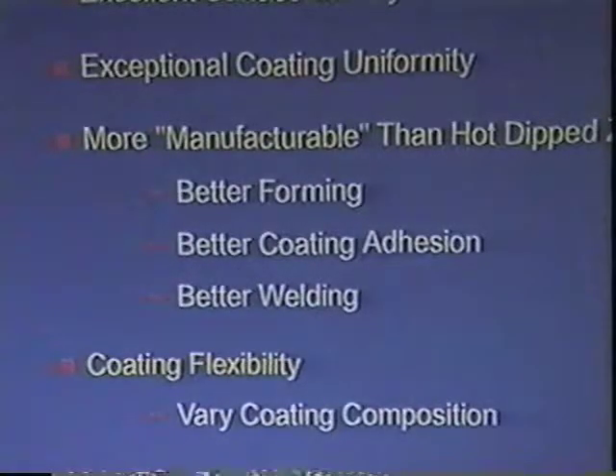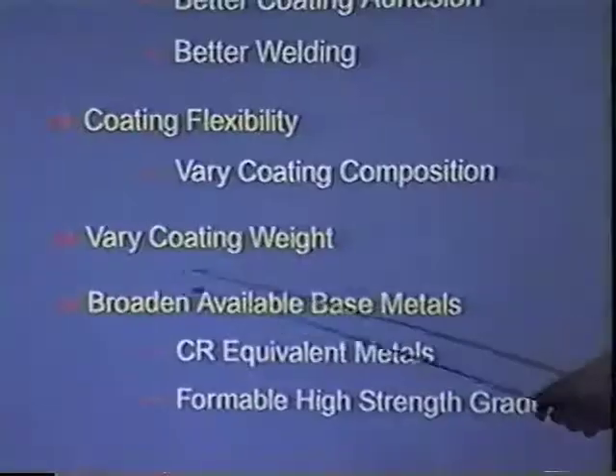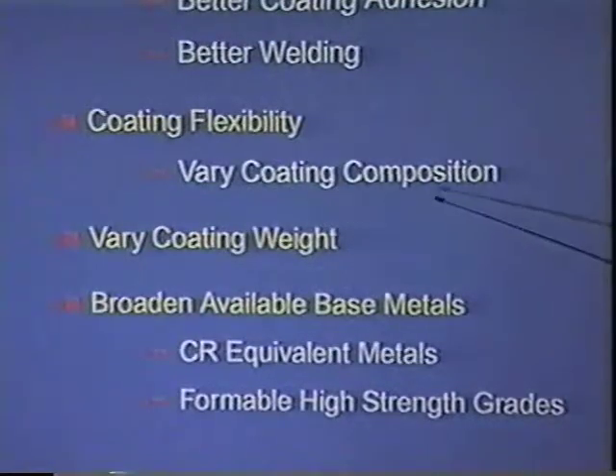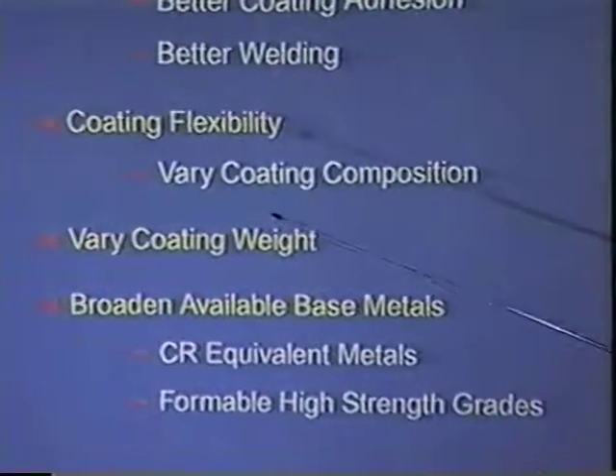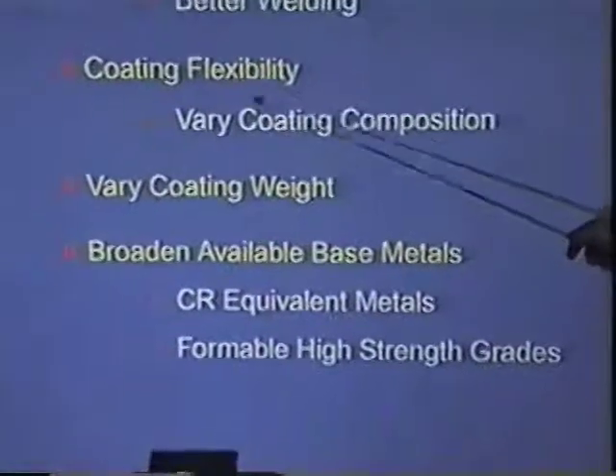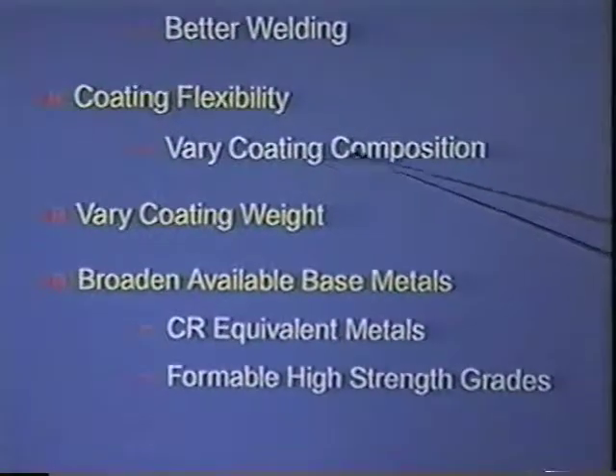Better welding. It's better welding than galvanized. But galvanneal, we talked about, the reason you get galvanneal is to get better welding. So galvanneal would be top welding, EG, and then hot dip. So there's kind of some play in there. Coating flexibility, well, if you want EG, then it's very flexible. If you want hot dip, then it's not the way to go. But you do have the choice of either making the zinc coating or the zinc nickel coating that's going around, so you have that variability.